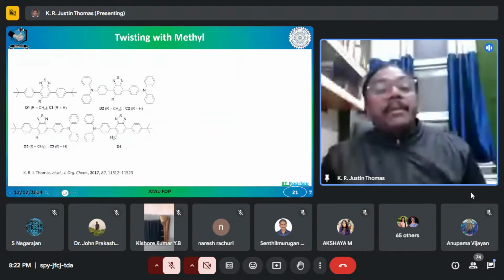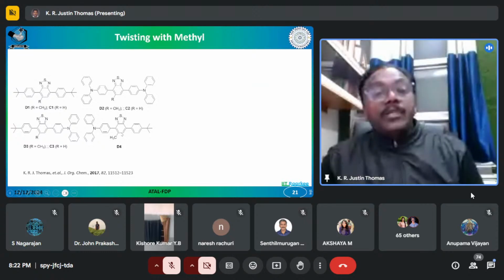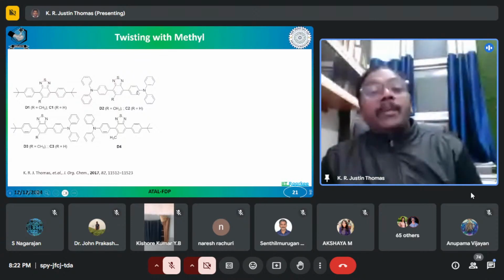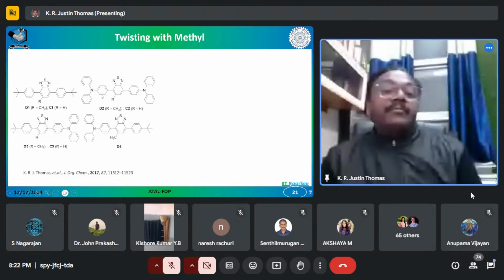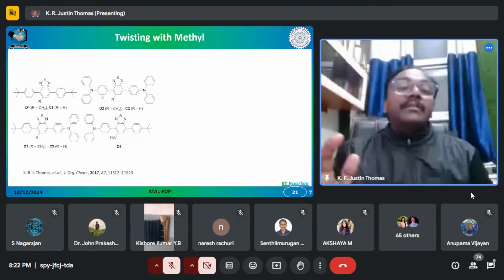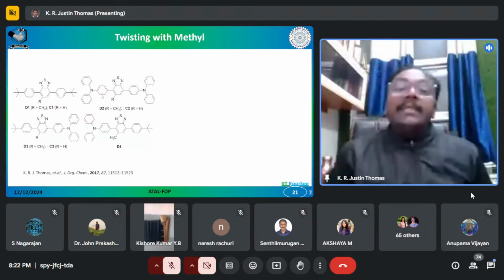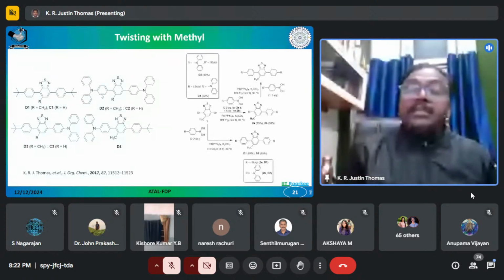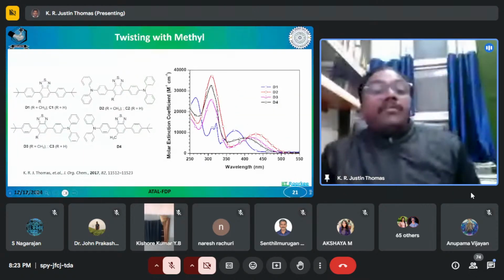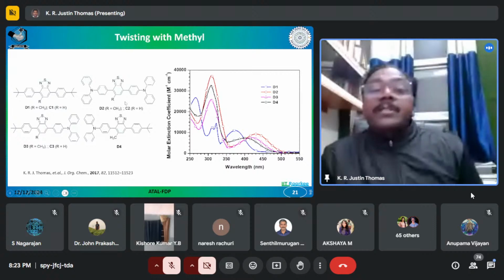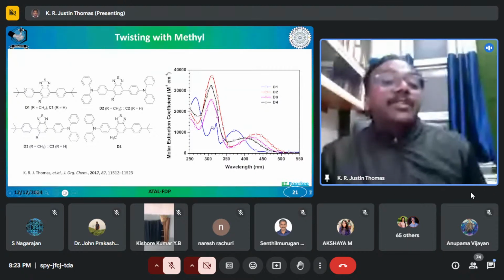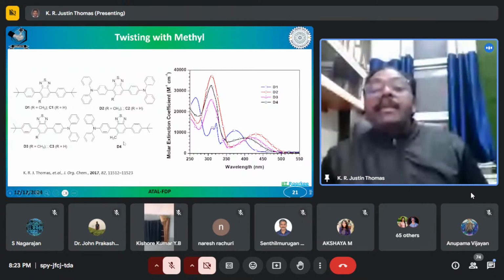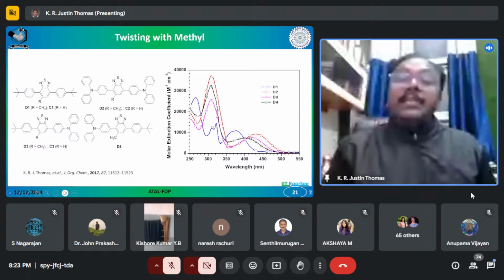Here, the donor group will be tilted because of the methyl group. So there will be a poor charge transfer here. Here, you will still have a charge transfer because you have two triphenylamine groups, and only one is tilted. Okay, so this will give some expectations to us in the absorption and emission characteristics. That is what is realized also. You can see here, as I have told, the charge transfer will be more pronounced in D2 and D3. You can see D2 and D3 having a redshifted absorption when compared to D1 and D4. D1 is not having any charge transfer characteristics and D4 is having charge transfer characteristics. You can see this very clearly here.